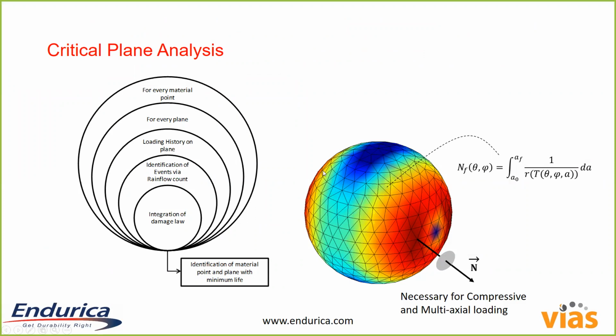I mentioned before we're using critical plane analysis, where for every point in the finite element model, we do a search over every possible plane on which a crack might start. We resolve the stresses to that specific plane. We do a rain flow count on whatever history occurs on that plane, and then we integrate our crack growth rate law using that information, and repeat that for every possible plane. Once we're done, we can see that the fatigue life depends on the orientation of the crack, and there will always be a particular orientation that results in the fastest rate of crack growth and the shortest fatigue life. That's what we predict as the orientation of the crack that nucleates, and that's what we predict as the fatigue life for that element of the model.